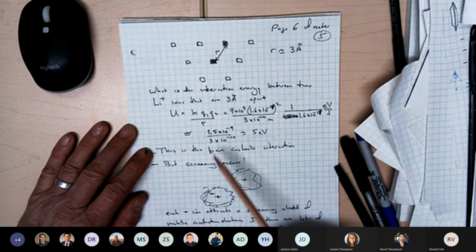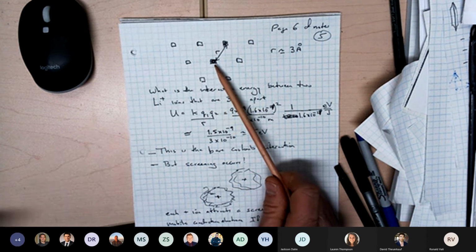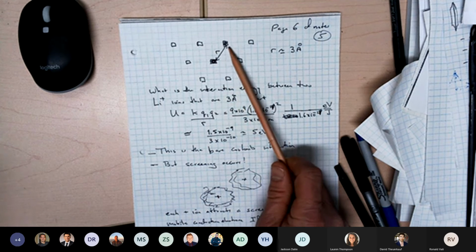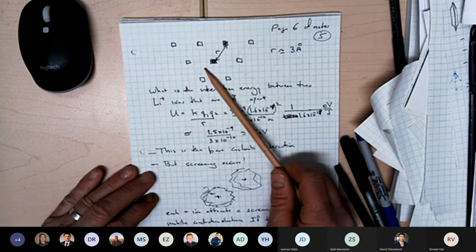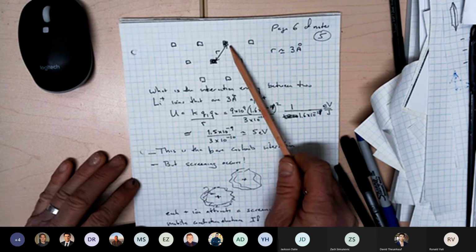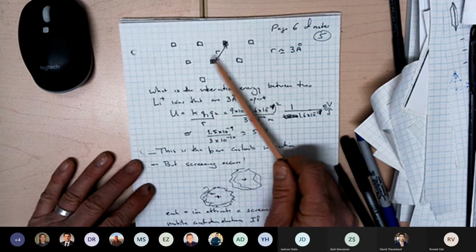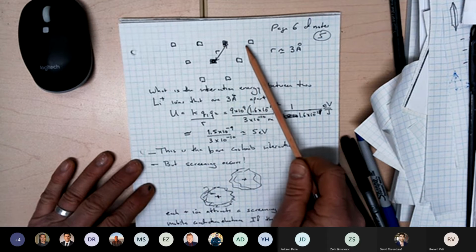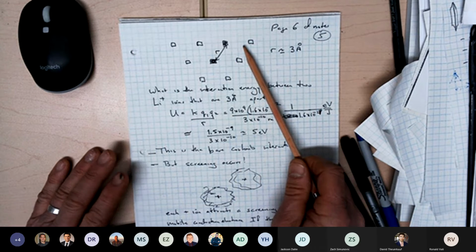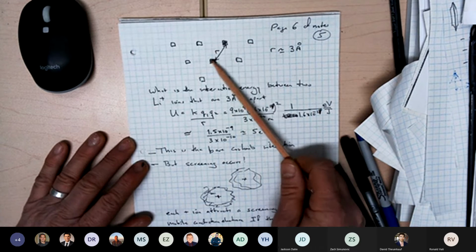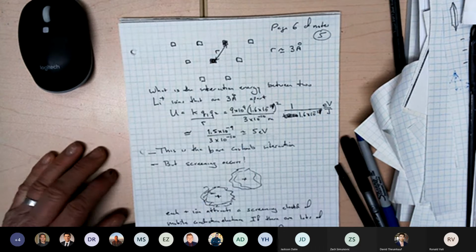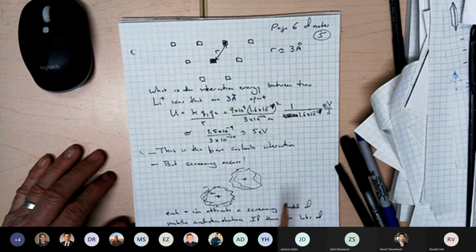It means that, okay, if you put the first lithium in, and that had a binding energy of 2 volts or something, if you put another one near it, it would be unbound. You couldn't put it there because it's only bound by 2 volts, and now you're asking for a 5-volt penalty. So you could never put a lithium atom in the near neighbor site. And we know from experiment that we can put lithium atoms in the near neighbor site in titanium sulfide and lithium cobalt oxide. So what's going on?